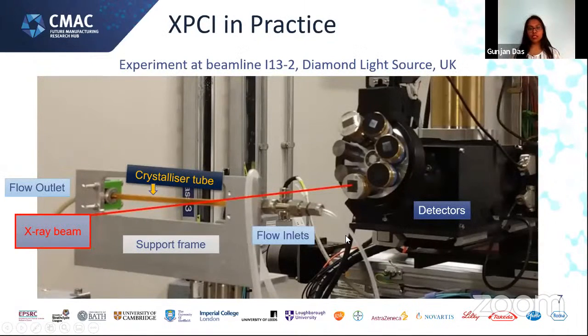So how does this work in practice? The experimental work has been carried out at the I13-2 beamline at Diamond Light Source. We have performed fast imaging paired up with XPCI. We have taken roughly 20 frames per second, and the aim was to visualize crystallization with a chemical contrast. So what we have done is we have performed imaging inside the crystallizer here.